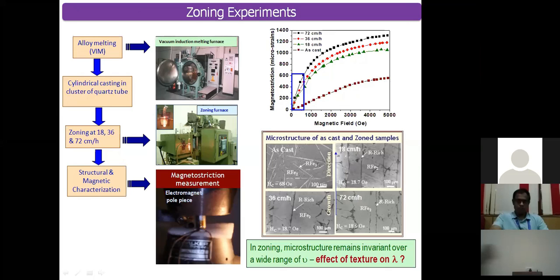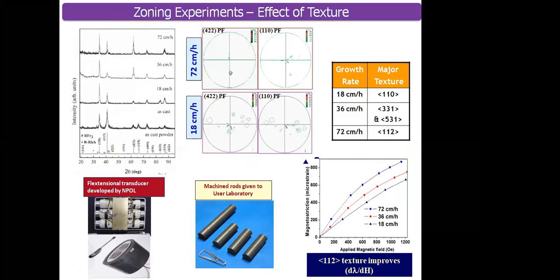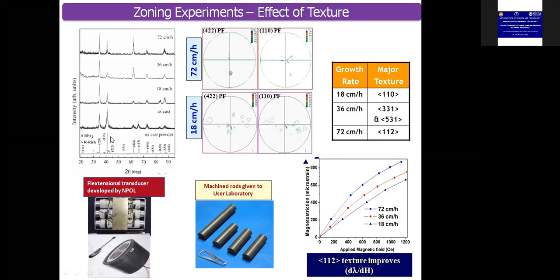So we went for measuring the texture using a technique called pole figures, where we used an X-ray texture goniometer. Before that, first we tried the conventional XRD. We cut the sample, because it's basically a rod sample, along the longitudinal direction and tried to see the XRD. From XRD, we could see some glimpses of a 112 kind of orientation, but this is not a complete technique. I'm not able to exactly quantify what kind of texture is forming. So the most viable way is the X-ray texture goniometer, where we can generate the pole figure and also quantify what kind of texture is forming.